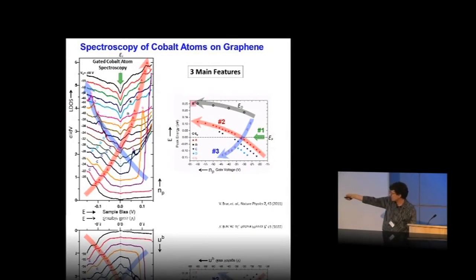To understand those better, I've plotted the energy of all these resonances here. This is energy versus gate voltage, and I've also plotted how the Dirac point moves with gate voltage. You can see that some of these features move with the Dirac point, and other features move opposite in energy to the Dirac point. The features outlined in red move with the Dirac point, which implies that they are density of states features, embedded in the band structure due to that impurity.